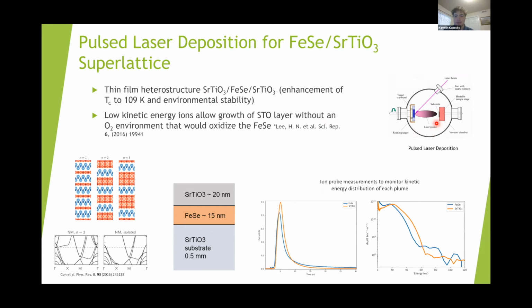Now, these samples are grown through pulsed laser deposition, shown here, where a laser ablates a target and ignites a plasma plume. And we placed a square Langmuir probe here in order to measure the ions of the materials in the plasma. This is to prevent oxygen incorporation into the materials, as this oxygen incorporation from the strontium titanate may affect the iron selenide quality. And this down here is the proposed layering form that we have.